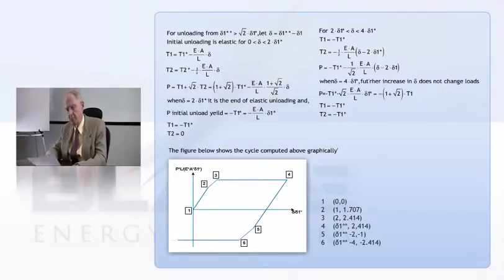When you start to test single crystals, you get closer to Masing's hypothesis. And I think that's because what happens in a single crystal is more like what these bars are doing, and they don't have the built-in work hardening that you would get from dislocations and such in a polycrystalline material.